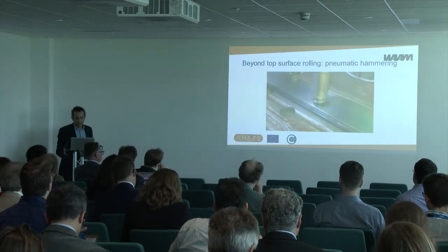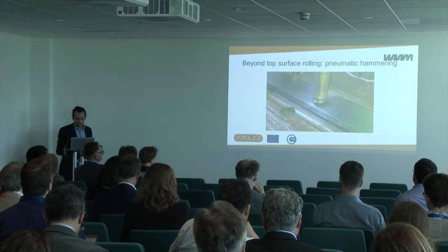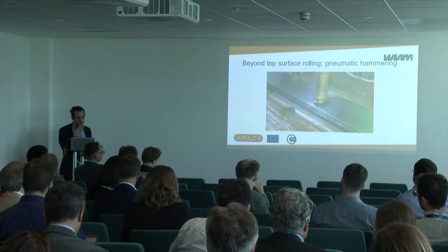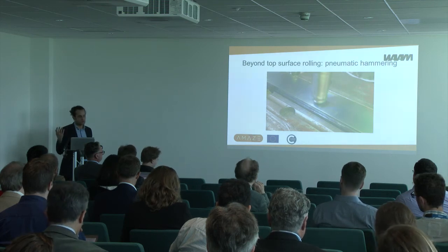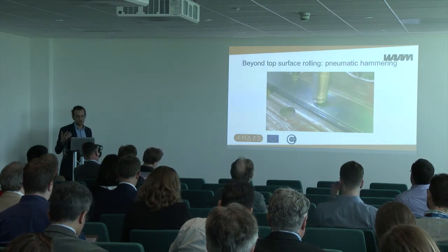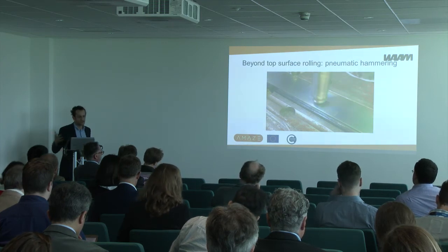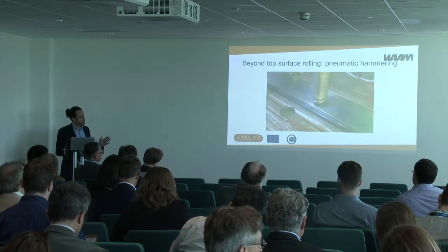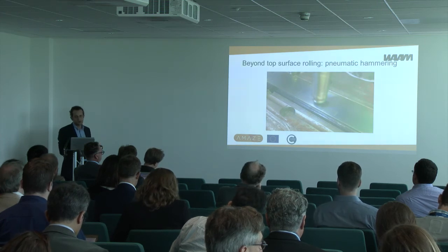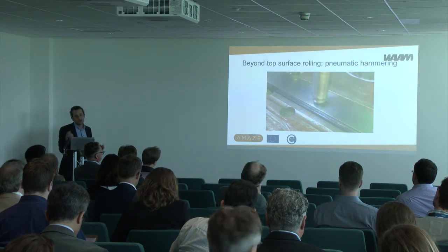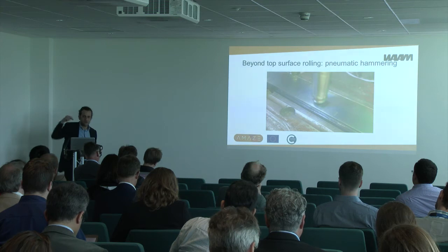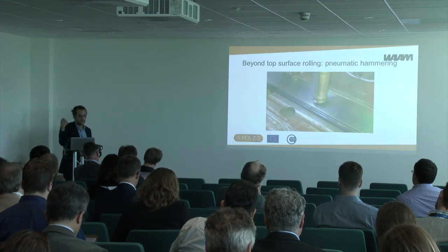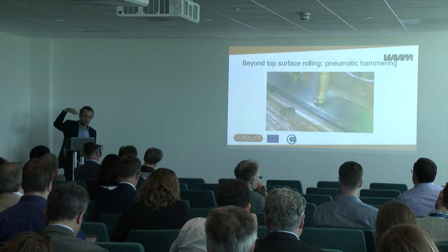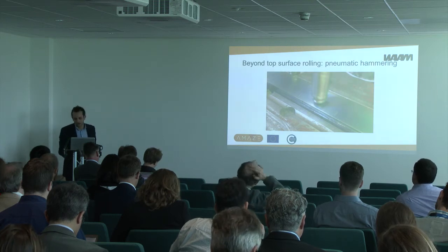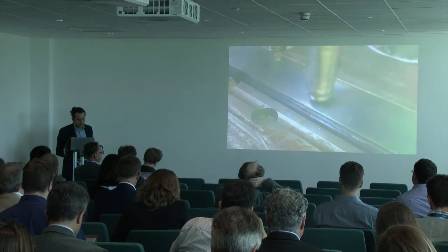It's what we call the pneumatic hammering. It's a very interesting piece of kit because, first of all, it can be attached to a robot, while the rolling, as you have seen from the charts, requires a substantial amount of load, up to 75 kilonewtons, so the machine is really big and expensive. Pneumatic hammering can be done robotically because the load is minimal. The kit is very cheap. The tool can be as cheap as $5,000. And then, because you can do it robotically, you can explore all the 6 degrees of freedom of the robot itself. So you can process pretty much any geometry, and you can go deep in the intersections where normally you couldn't have access using the roller. So that's the way it works.